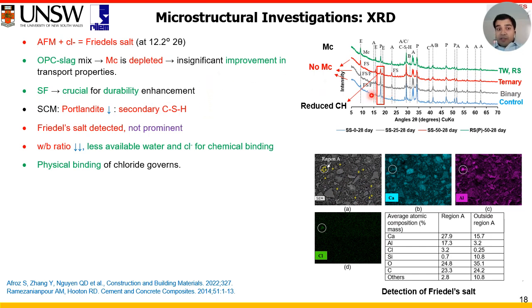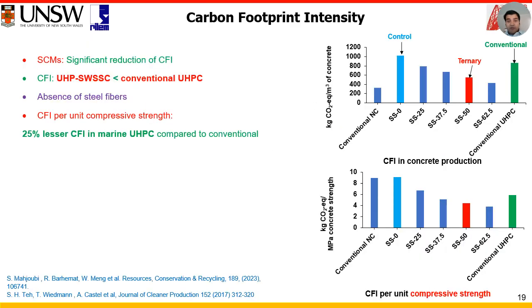We detected Friedel's salt, however the peaks were not prominent, and from the EDS mapping, in some rare instances we located regions rich in Friedel's salt. We came to a conclusion that as the water to binder ratio is very low, the available water and thus the available chloride for chemical binding is also significantly less, which indicates that the physical binding of the chloride has governed in this type of concrete.